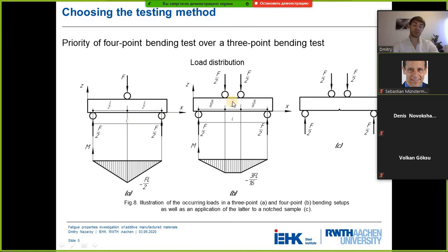Therefore, it was chosen to take the 4-point bending method because a broader amount of material is brought to the maximum force. It's more convenient. But it should also be noted that a decision was taken to create an artificial notch because it's meaningful. Without this notch, it was uncertain when and where the crack would appear.